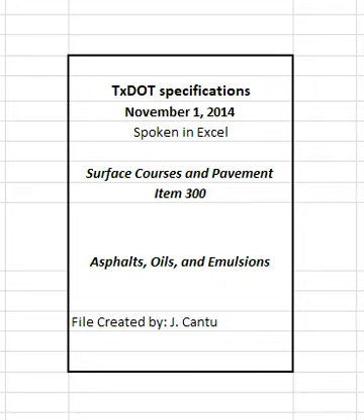Cure films for 14 days at 75 degrees Fahrenheit and 50% relative humidity. 5. Cut samples for tensile strength determination using a crosshead speed of 20 inches per minute. 6. Specimen must remain intact after exposure and removal of excess rejuvenating agent. 2.5 Specialty emulsions. Provide specialty emulsion that is either asphalt-based or resin-based and meets the requirements of Table 11.